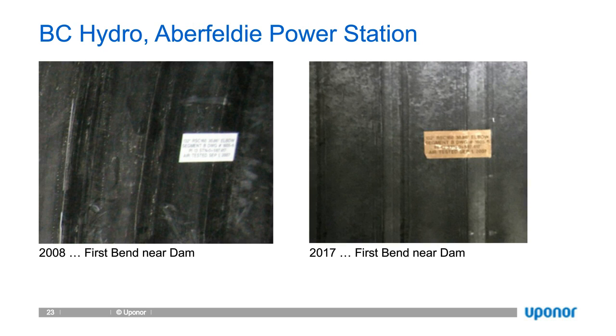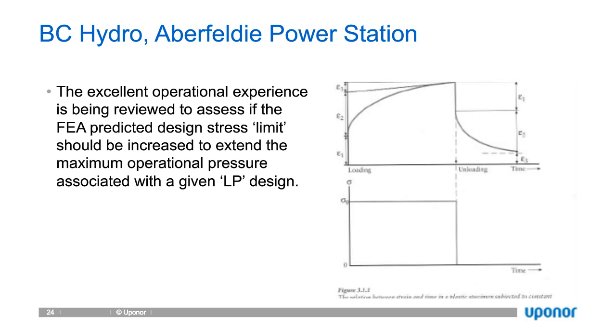Because the velocity in this pipe is 8 to 10 feet per second. It's at the first 55-degree elbow where there's considerable turbulence. So again, no evidence of wall deformation or any evidence of slow crack growth formation near the ribs. And a final slide here.